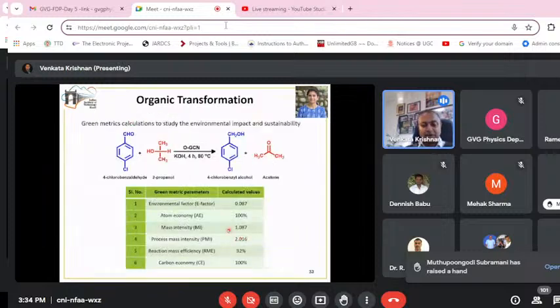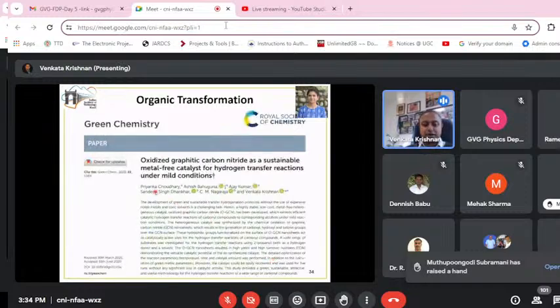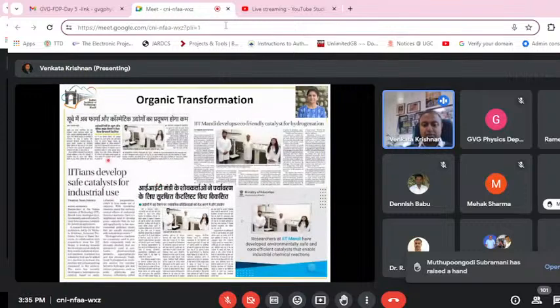Then we again evaluated the green metrics parameters. Herein we evaluated the environmental factor, atom economy, mass intensity, process mass intensity, reaction mass efficiency, and also the carbon economy, and we got relatively good values for each of these cases. This work was also published in the journal Green Chemistry with my former PhD scholar Priyanka Chaudhary as first author in 2020, and this work also got some media attention during the time of its publication.